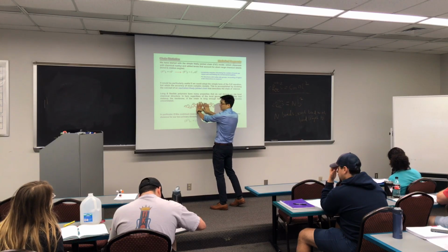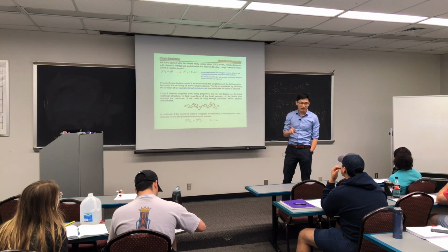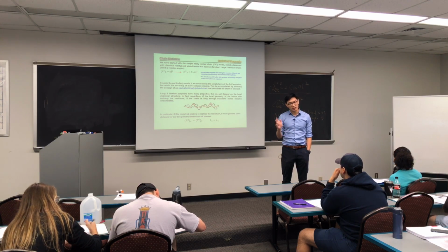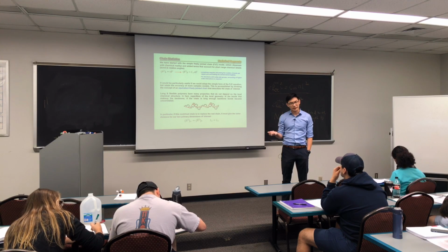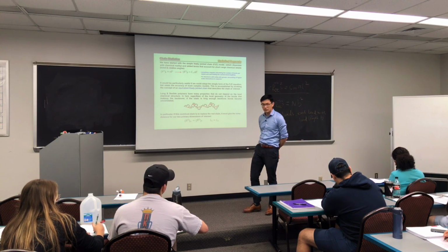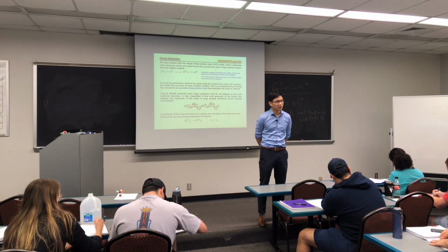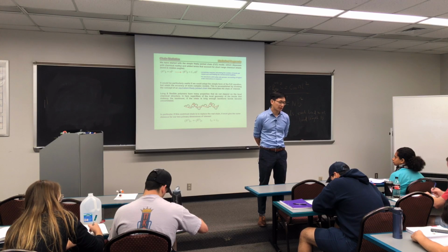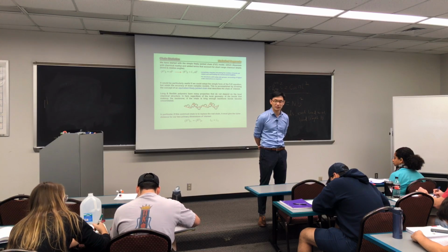If I cover it up again, you don't see what's inside. We call them statistically equivalent for two different models. Why? Because they behave similarly in terms of end-to-end distance, and they behave similarly in terms of contour length. In doing so, by converting a non-free joint chain model to a free joint chain model, we simplify the math so much that we can calculate a lot of parameters very straightforwardly and easily. Okay?